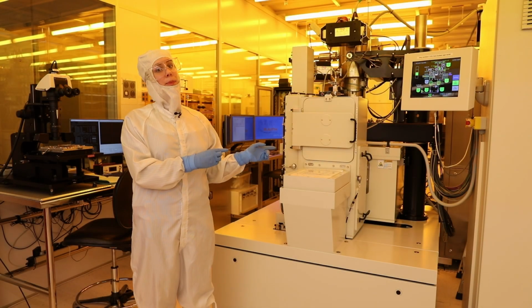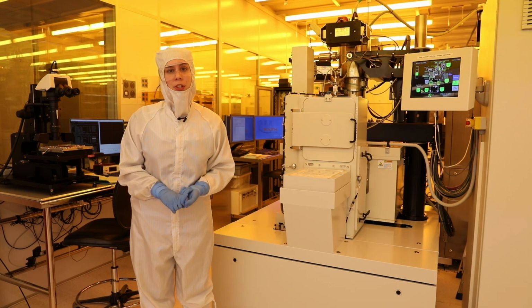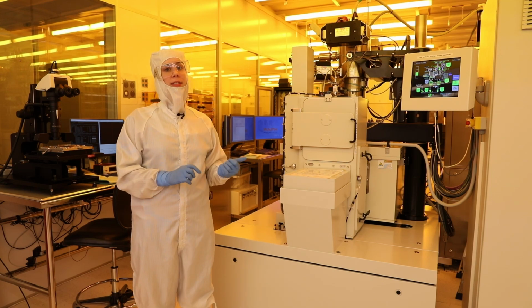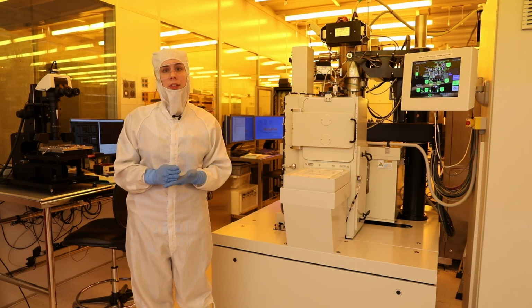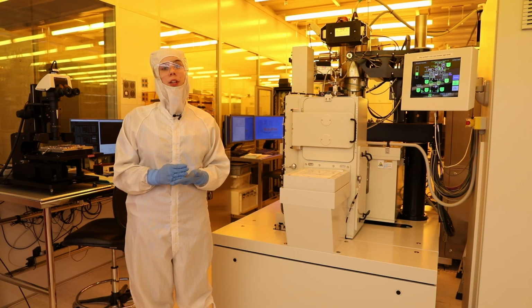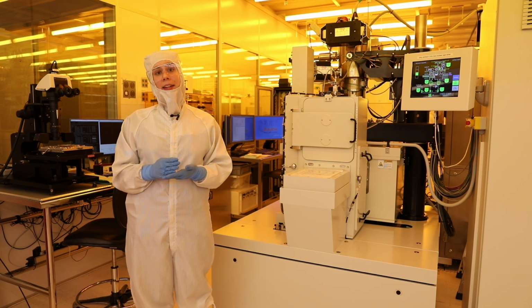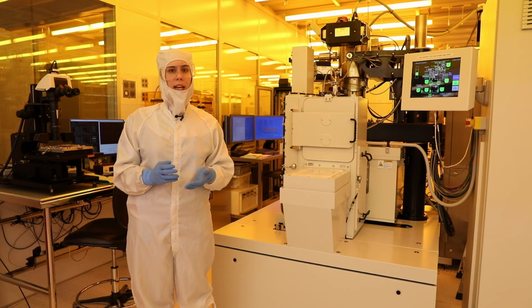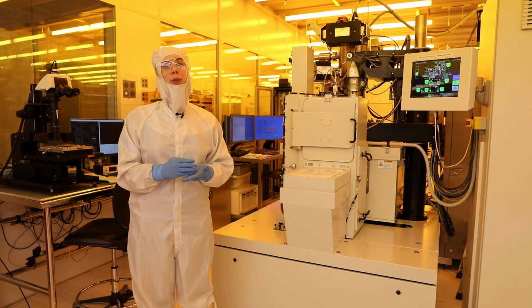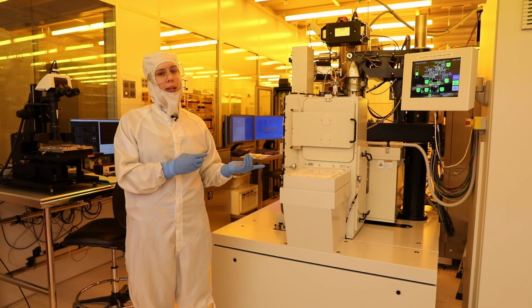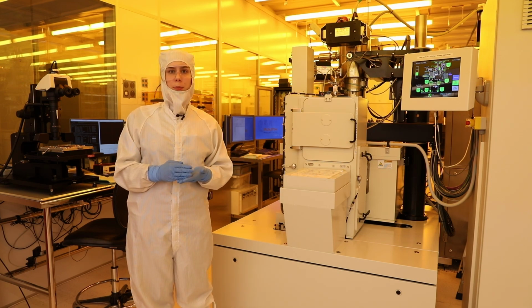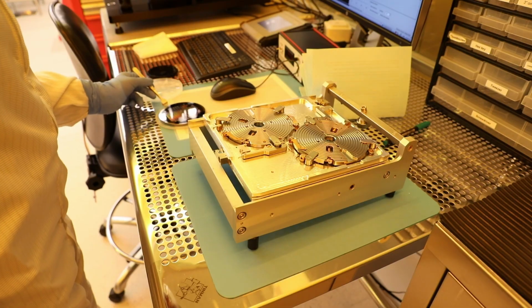So this magnificent beast is an electron beam lithography machine, and what it's going to do to our resist is the same thing as the laser writer did, except it's going to do it with a 100 kilovolt electron beam. So the mechanics are very different, but the principle is the same. We have a resist into which we're going to draw a pattern using the electron beam, which is going to make the pattern soluble in a developer solution.